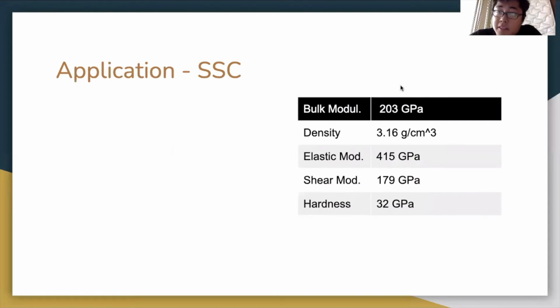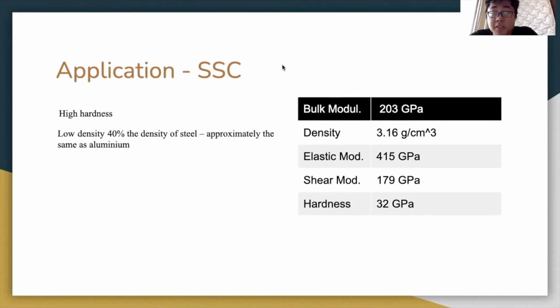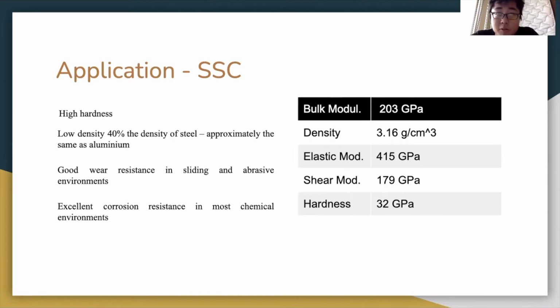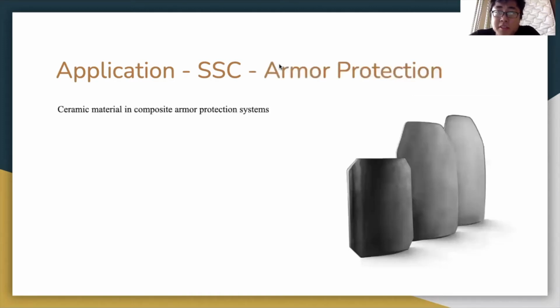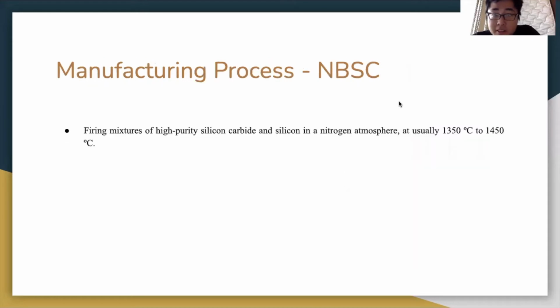And here's the table of SSC properties: density, bulk modulus, Young's modulus, shear modulus, and hardness. And as you can see, it has a high hardness, it has a low density compared to other steels, approximately similar to aluminum, and it has a good wear resistance, and it has an excellent corrosion resistance. So this is pretty good in composite armor protection systems. As you can see, this picture shows one example of the armor system, because of its high hardness, compressive strength, and elastic modulus. And now let's move on to the next part of silicon carbide.